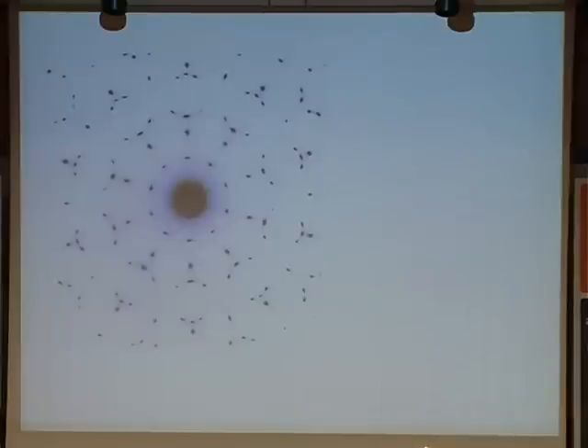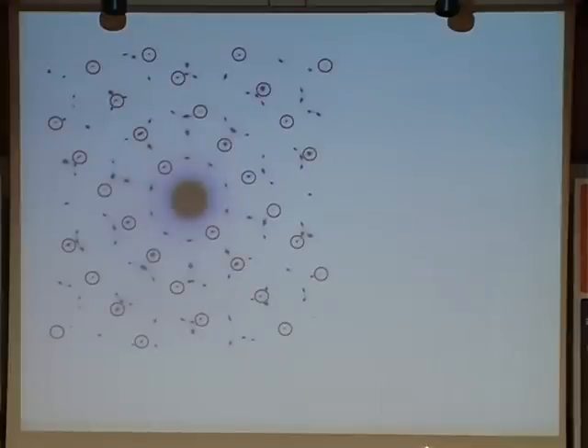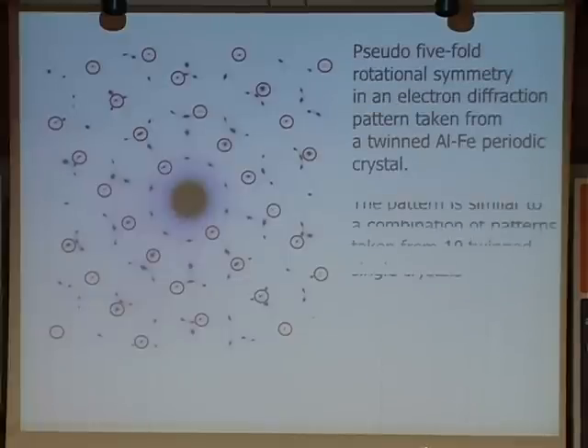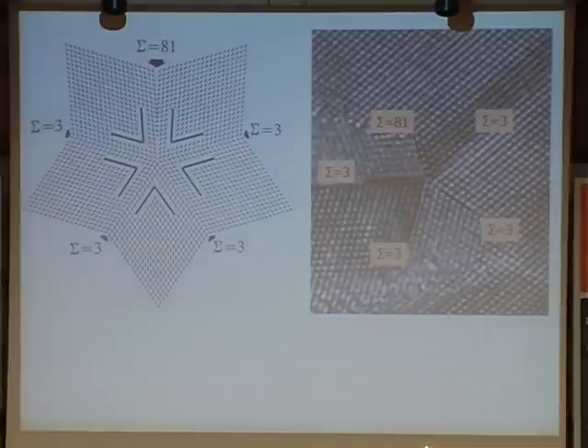But in fact, we know that these are indeed 10 twins, and you can take the diffraction pattern, as I had, from each individual one, and you can show that it is something like this. Each individual one will look like that. And you have 10 of them that form the whole. In fact, if you do that, you have 5 of them, but let me tell you why. Because 2 twins which are opposite to each other like that have exactly the same orientation. So we have 2 like this, 2 like this, 2 like this. Altogether, 10 twins, but 5 diffraction patterns superimposed. Okay, so this is what I had in mind when I did this experiment.